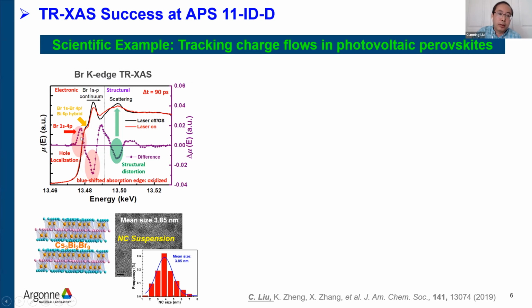Here, I'm not going into the details of how we understand this experimental data, but I just want to say that from this difference spectrum, the positive peak tells us the photo-generated hole is localized at the bromine site in this nanocrystal, and from this negative peak, we can know the local structure around the bromine site is distorted due to the hole localization. By the way, here we did the TR-XAS measurements by probing the bromine edge.